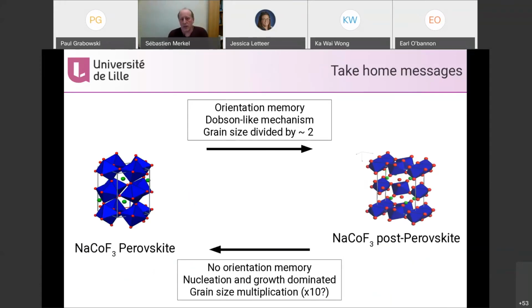The take-home messages from that experiment is that if you go from perovskite to post-perovskite in NaCoF3, well, you get a Dobson-like mechanism with orientation memory. It's a martensitic-like transformation with a division of grain sizes by 2. And then if you go back to perovskite from post-perovskite in this compound NaCoF3, the grain size gets multiplied by a factor of 10.